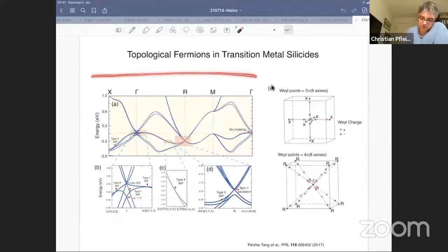Right, it's a cubic compound. This is the band structure, and you can find these crossing points here at the zone center, and then at the sides of the zone, at the R point and the M point. There are also these types of crossing points. There's one thing that's very interesting, which is not explicitly discussed in these papers. You can already see the effects of these nodal planes in these band structures. So this is a band sticking, which is enforced by this non-symmorphic symmetry. And if you look a little closer, in these zoom-ins, you can see that there are all sorts of crossing points floating around.